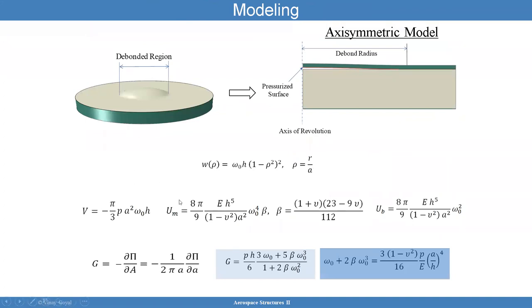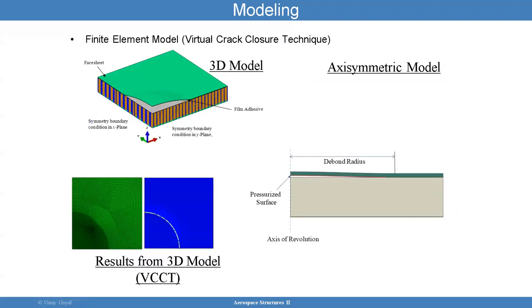These formulas use energy principles for plate theory. Bottom line: given the pressure, the modulus, the crack size, and the thickness of the face sheet, you can come up with omega naught. Once you calculate omega naught, you can plug it into this equation to get the energy release rate. This is meant to be a first-order calculation — you definitely want to do finite elements as well.